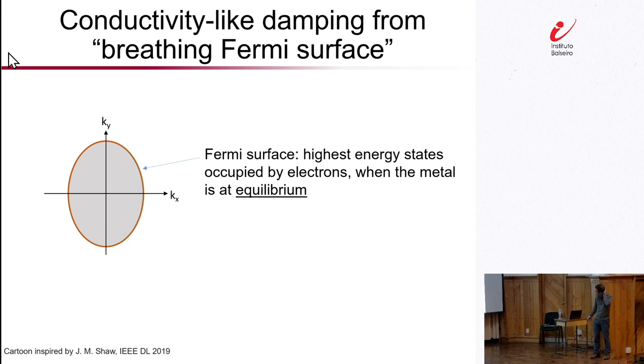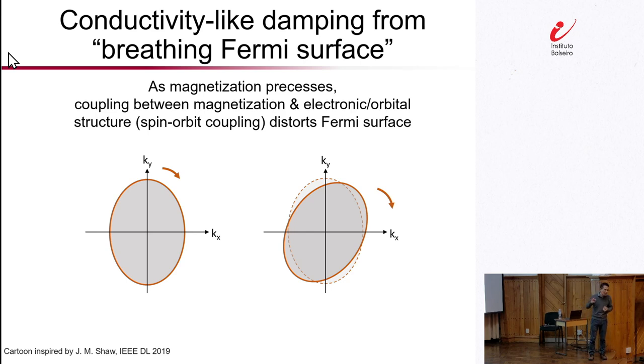Okay, so this is where a rather nice model, what's called a breathing Fermi surface model, comes to our rescue. Going back to your class, solid state physics 101, we have this Fermi surface which captures the highest energy states that are occupied by electrons, but the key word here is at equilibrium, right? Technically speaking, we are not at equilibrium. We are exciting the material. The magnetization is precessing, so we are somewhat out of equilibrium. As the magnetization is precessing, because there is some interaction, what we call spin-orbit coupling, between the spin magnetic degree of freedom and the electronic, or if you will, the orbital degree of freedom, the Fermi surface itself actually changes. The shape of it becomes distorted.